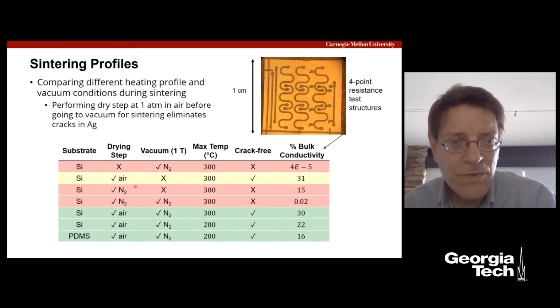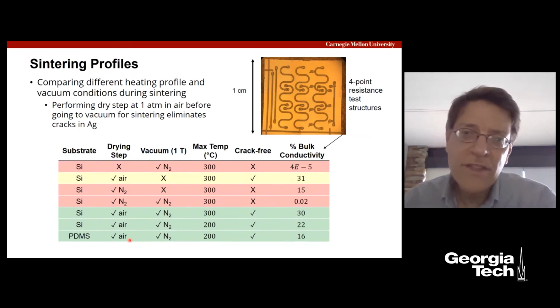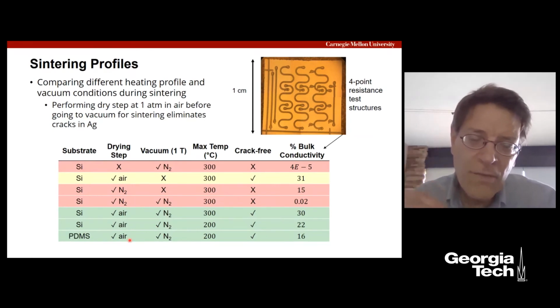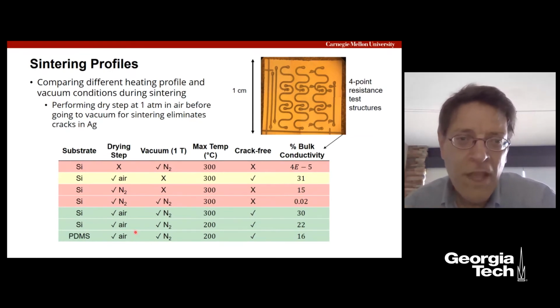Okay, so the first one was no drying step. We had drying steps for all the other ones. So it's important to do the drying step in air, so that we get the good, high conductivity of the silver, but we also get no cracks, because we're able to do the drying first, and then we can go into this inert environment. And what we found is we can lower down to the 200-degree temperature and get reasonable conductivity and do a trade-off.